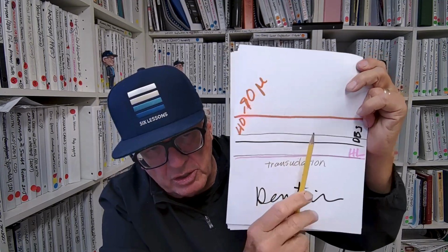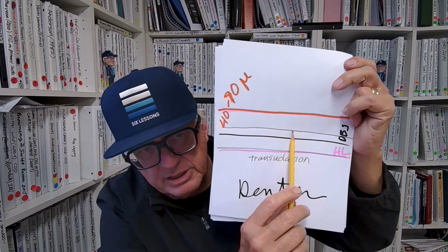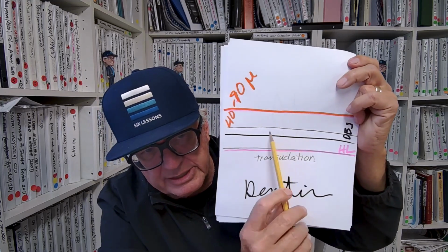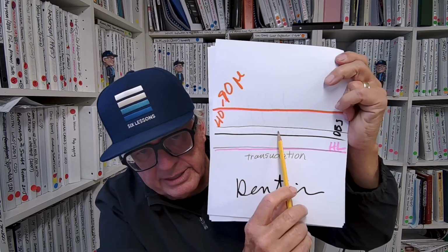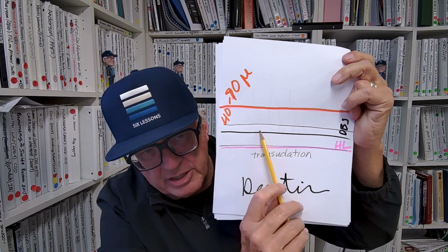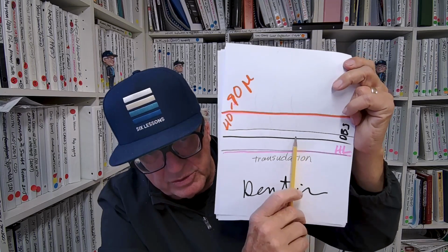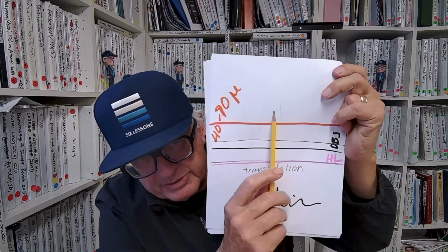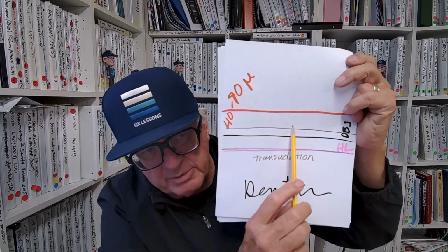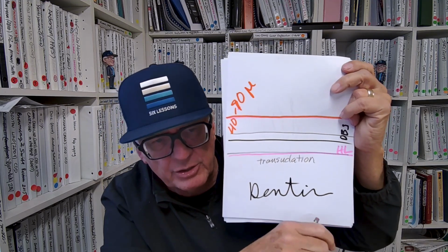So this is called a diffusion polymerization. And now you're polymerizing this layer of oxygen inhibited monomers, and they start polymerizing and getting hard, and this shuts off the pulpal tubule transudation that's coming up. But this diffusion polymerization is something that happens with light cure, but it has to have a flowable composite component.